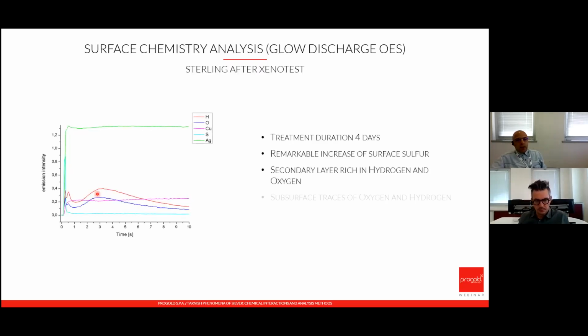The same sterling alloy, after 4 days in the xenotest machine, showed a relevant increase of surface sulfur coupled with silver, oxygen and hydrogen, revealing the important catalytic action of ultraviolet light. Important is that copper is also almost absent on the surface, as you can see here.